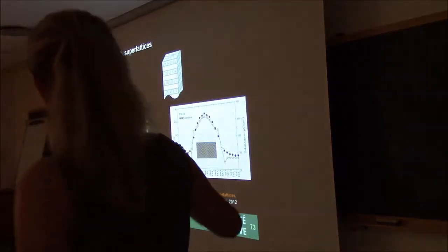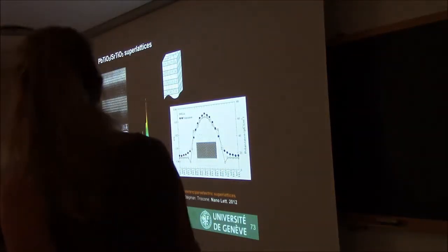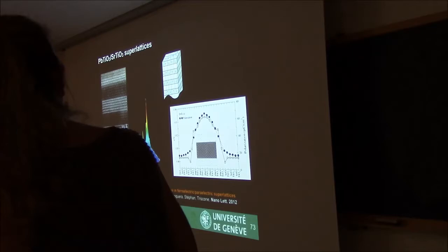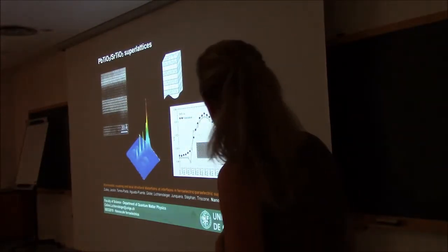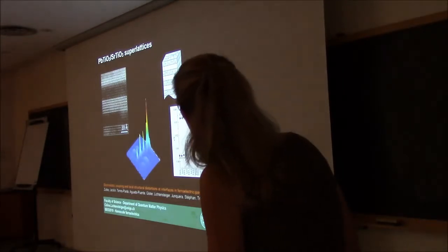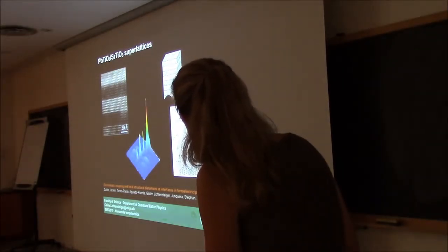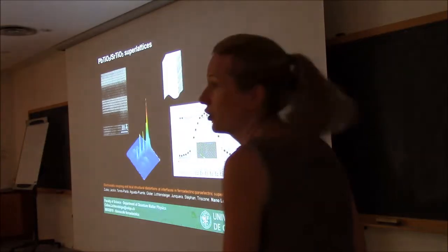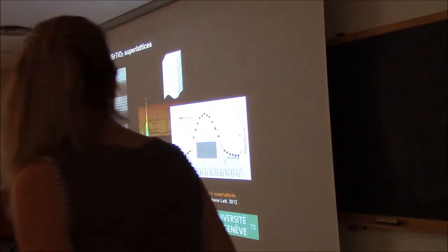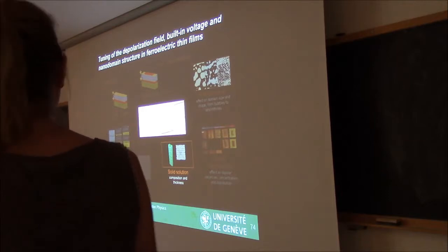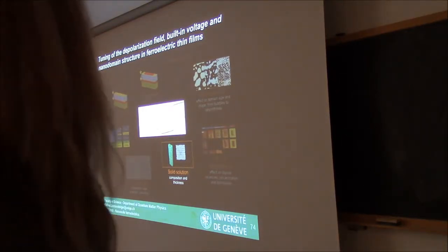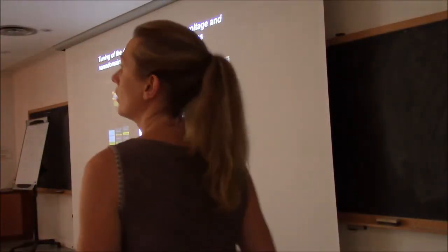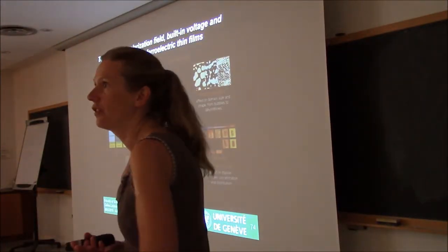In these superlattices, so before, the improper ferroelectricity was in the superlattices where the polarization was uniform. But, of course, if you change a bit the conditions, you can also have polydomains. And here in this case, we had polydomain superlattices, and again, depending on the proportion of PTO and STO and so on, we were able to see that it's not just that they are polydomain, but actually that you have these flux closure domains between the different domains. And solid solutions. Okay, so with the superlattices changing the periodicities, the size of the different materials and so on, you can completely change the configuration of your polarization.